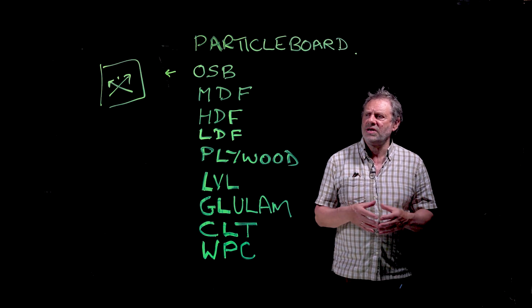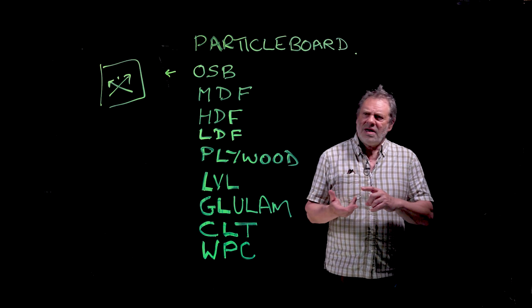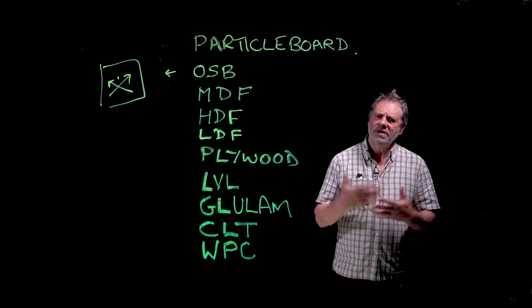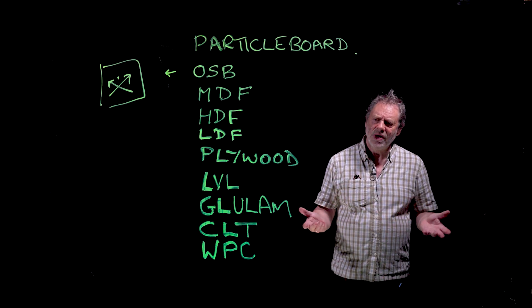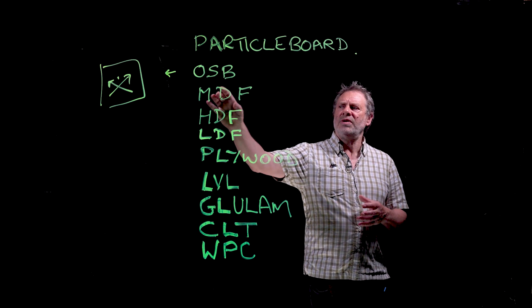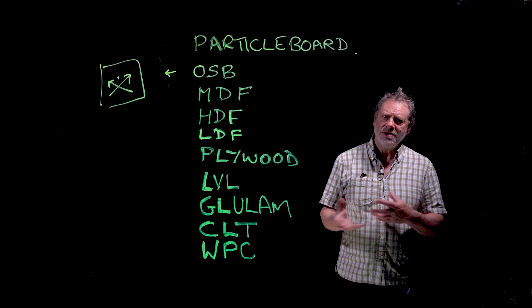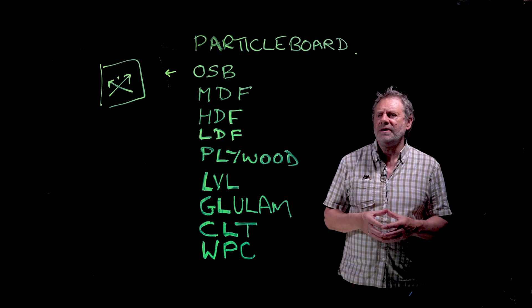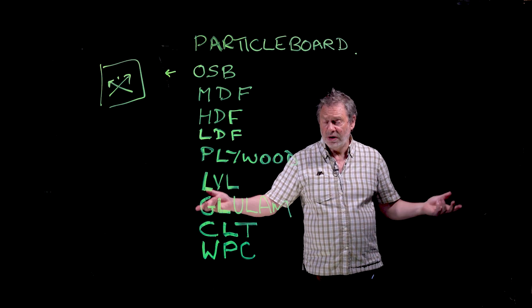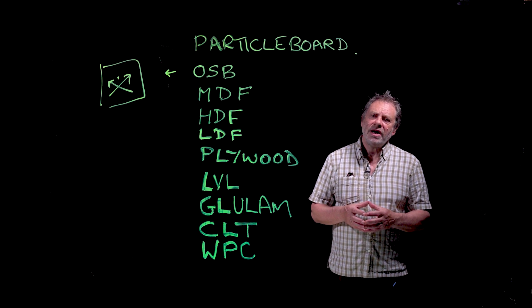MDF is used mostly for higher-end furniture and for door frames, but not so much for window frames, because if water gets in, the fibers will swell even if you have a moisture-resistant adhesive. There has been a development where an MDF product is made using acetylated fibers, which now have dimensional stability, allowing large long profiles to be made for windows, doors, and exterior joinery applications.